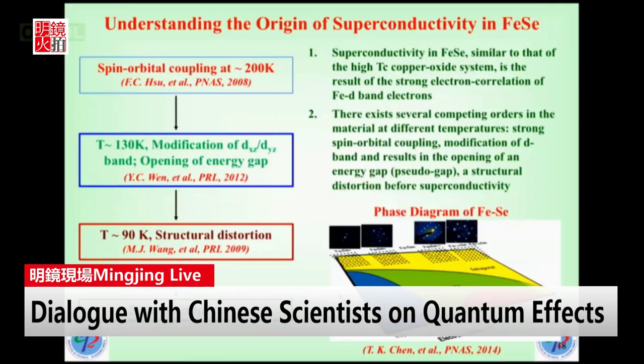So in the last 10 years, we have spent a lot of effort, and many people work on that. So there is some understanding from high temperature down to low temperature when it becomes superconducting. And similarly, there is such a phase diagram predicted, or we propose essentially, similar to what I just showed you for the copper base. The superconductivity in this iron selenide is similar to the high-TC copper oxide, which results from strong electron-electron correlation. Okay, and as I show here, there are many competing orders, competing states again, to get to this result.